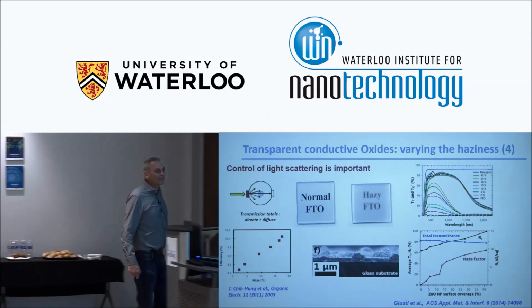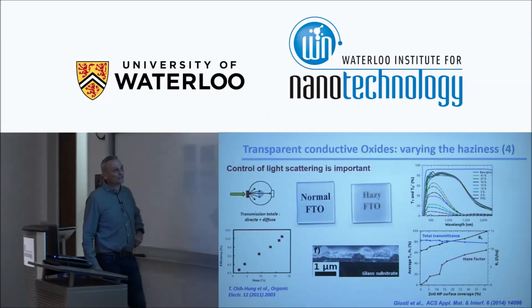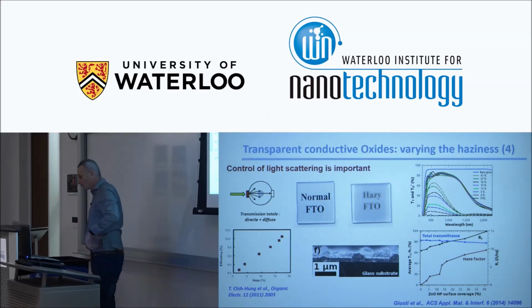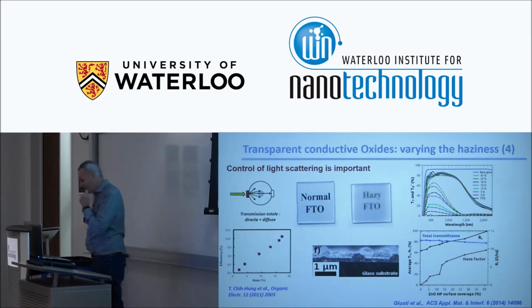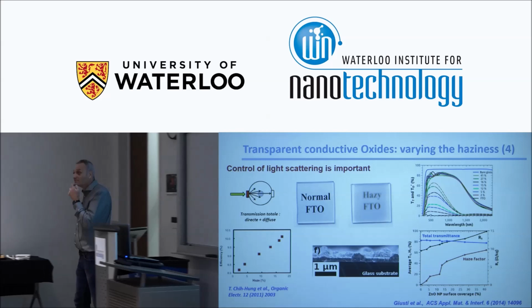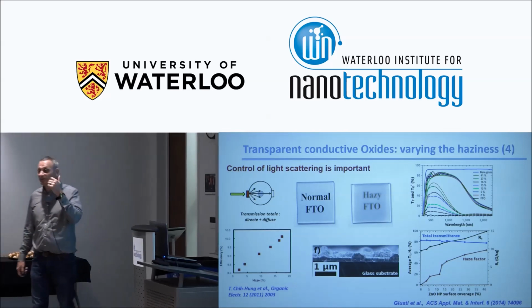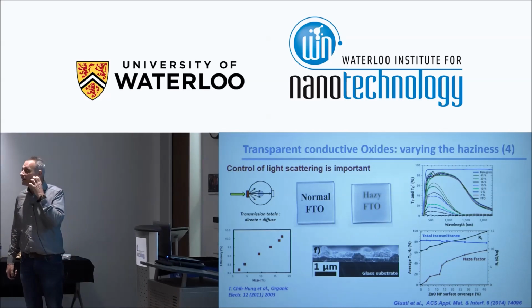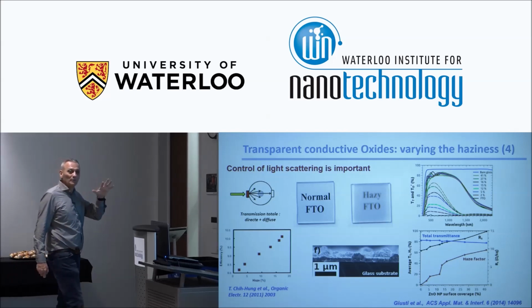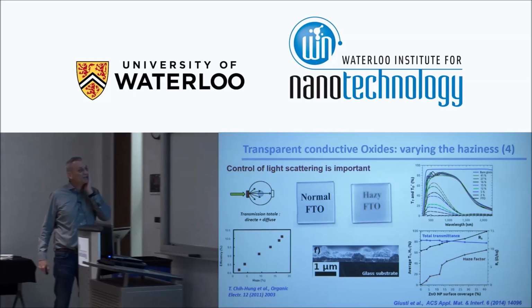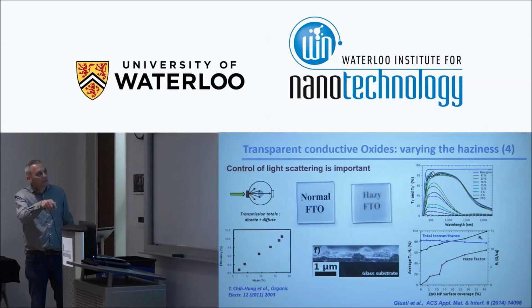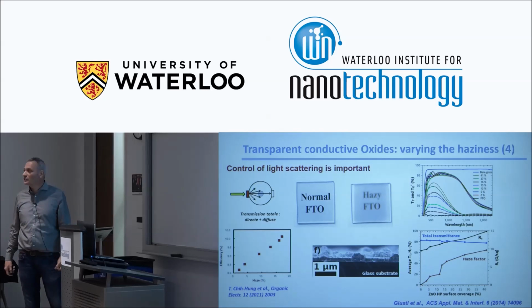On paper, it's very simple and easy, it should work, but then we tried with 3 different types of solar cells with experts in these solar cells, and the integration problem is not that easy. So we had some problem with delamination, for example. The solar cell works well with commercial FTO, but with our FTO, especially a diffuse one, it's a bit rough, so there could be some additional problems.